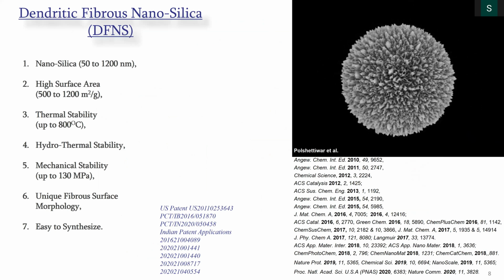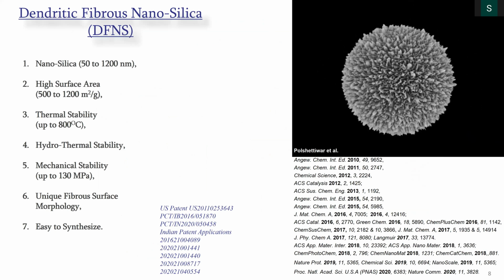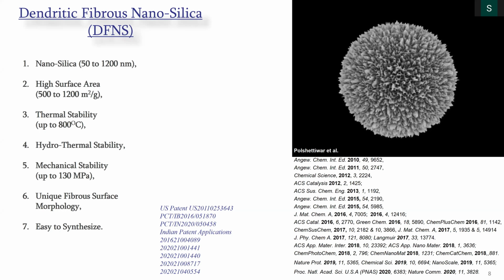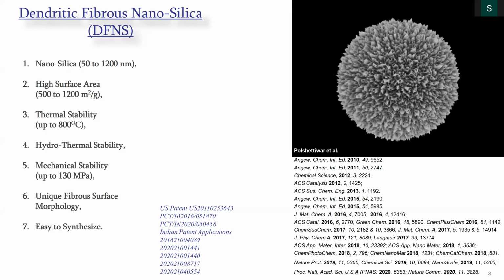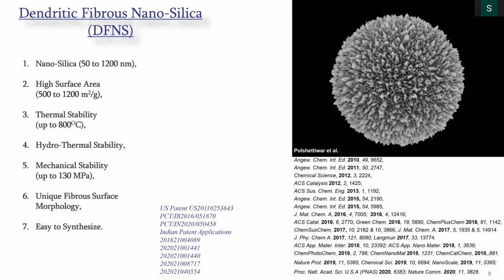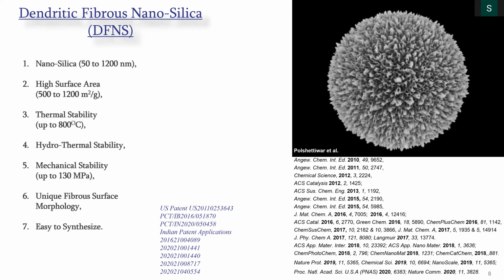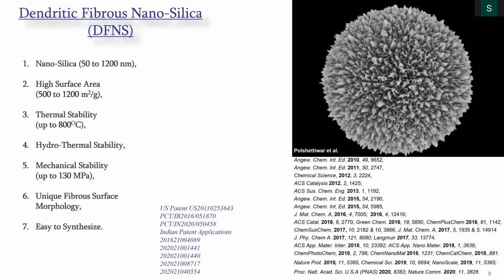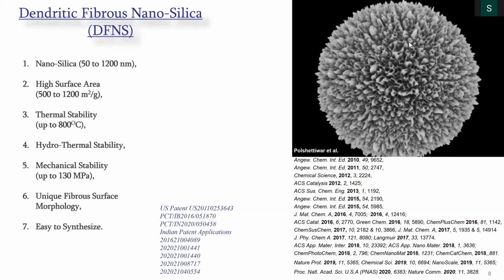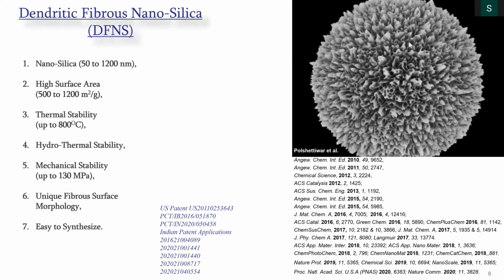So one can have a particle size from 50 to 100 nanometer, 100 to 200 nanometer, up to 1.2 micron size. Based on the application, for drug delivery, you need smaller particles. For other applications, you need bigger particles. We can also tune the surface area.